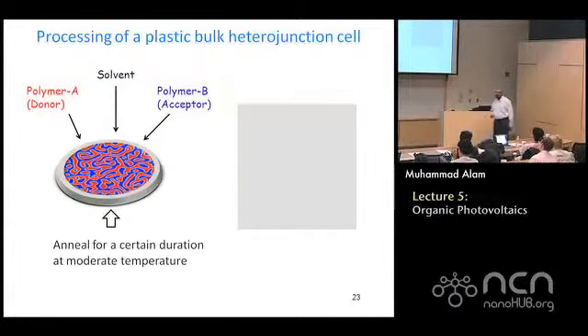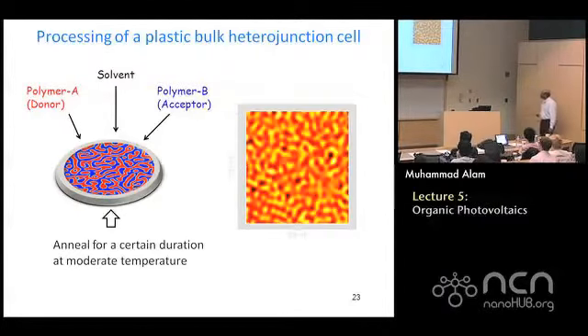Most of the time, if you put salt and water and put it in your microwave, they get homogenized. They don't get phase segregated. But these polymers are such, and their surface tensions are such, that if you put it in here, like spoiled milk, they get phase segregated. So this is called spinodal decomposition. And here is a cartoon that Bishwajit made, and look at how, as a function of time, these two structures get phase segregated.